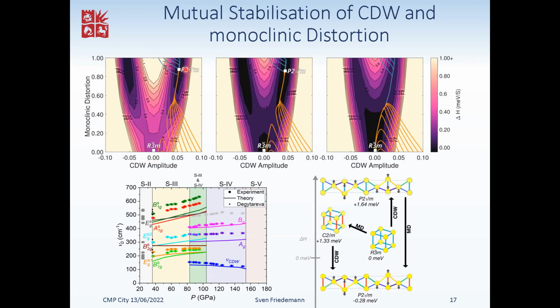And you can see the minimum here is at a finite displacement due to the charge density wave, and also a finite monoclinic distortion. This remains the case to some intermediate pressure, where you've got then two minima separated by a very small, very shallow barrier in between, and hence you can imagine that you can have a first order transition from this minimum to that minimum, this barrier being smaller than the thermal energies when doing experiments at any sensible temperatures, so room temperature or down to 50 Kelvin even. You can imagine that the sample is just fluctuating between those two, so hence it becomes a weak first order transition.